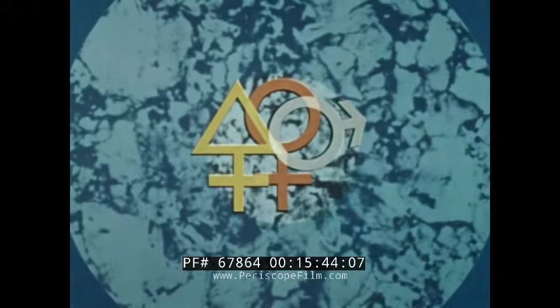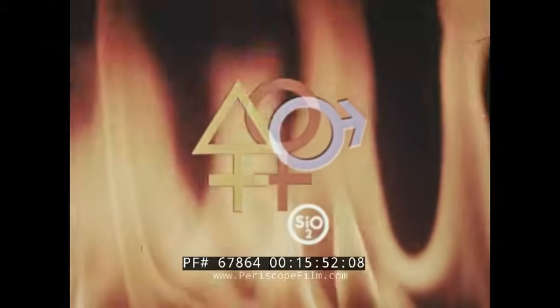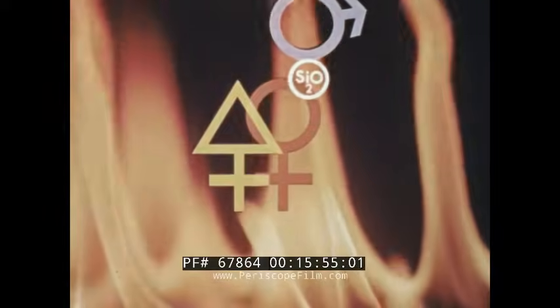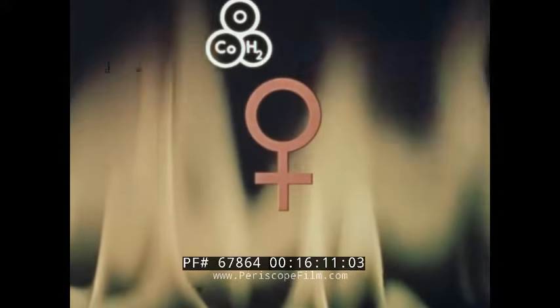In addition to copper, this 30% concentrate contains iron and sulfur in chemical combination. Heat alone will not break these chemical bonds. To separate the iron, silica rock is added. The iron combines with silica to form a slag and is drawn off. To remove the sulfur, air is introduced. The sulfur reacts with the oxygen and goes out as a gas. To remove the excess oxygen, which remains, reformed natural gas containing carbon monoxide and hydrogen is injected. This process results in copper more than 99% pure.